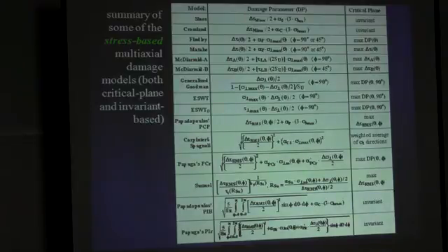Also, we have quite a lot of damage models. This is just a sample of the main stress-based models. We also have the strain-based and energy-based ones. What we can see is that you have too many of them. One of the challenges is to have enough data to figure out which are the best parameters that should be included in these damage models. All of them also have coefficients that need to be calibrated, the stress scale factors, which are different in each model, but in each model they are constant, at least for a given fatigue life.